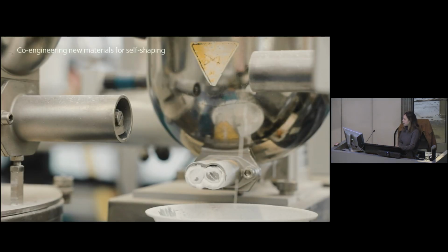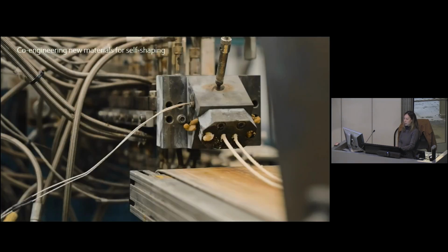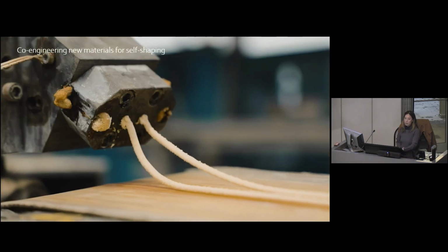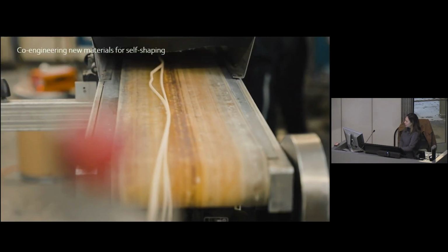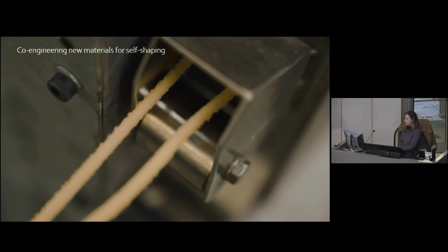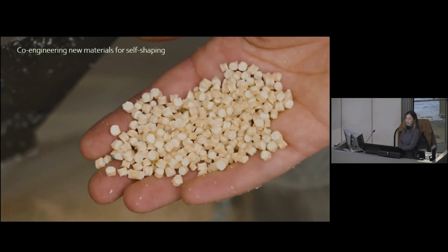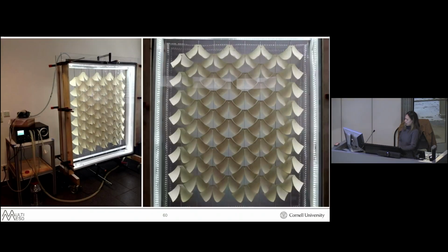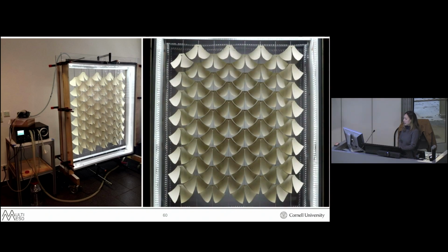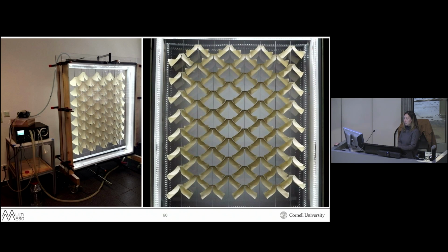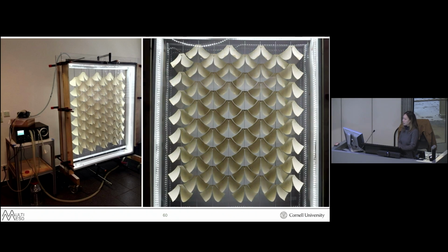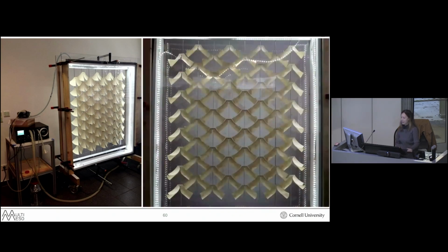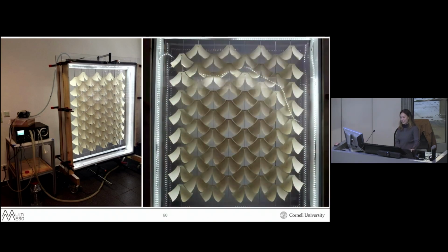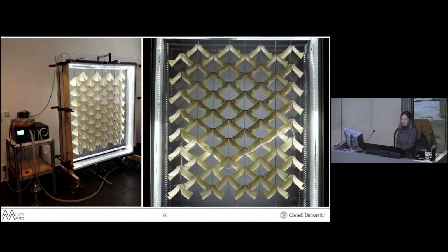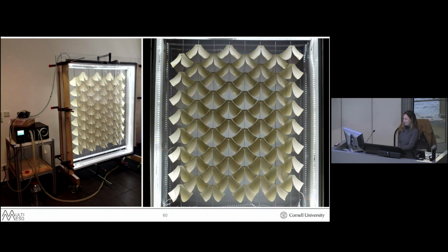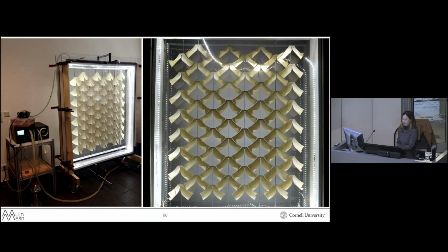And then we needed to design a material to match the response time to the time scale of weather changes in Freiburg. So together with the material scientists, we developed a highly responsive filament material consisting of 35% cellulose content by mass ratio. We went through a very extensive testing process in the lab using an active microclimate generator to cycle many times, alternating high and low humidities, where we discovered that our LED adhesives were not very robust against high humidities, but also that our 4D printed materials could continue to operate against the disturbances, unfazed by multiple attacks.